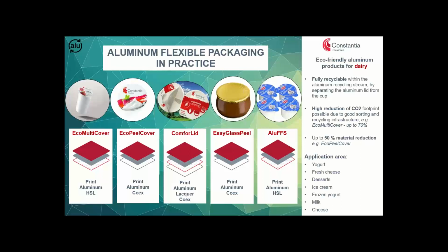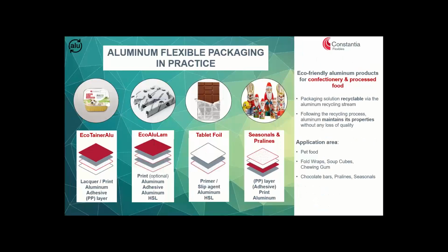The fourth product here we call Easy Glass Peel, and this is an aluminum die-cut lid or a reel-fed lid that is perfect for sealing on glass. It comes with an improved tearing resistance, and it is suitable for treated glass. It is available printed, unprinted, or embossed. The last product on this slide, Aluform Fill Seal, are basically printed alu reels or reel-fed lidding that are delivered like you see them to the customer. And on this product, I want to point out that it can include up to 70% of recycled content.